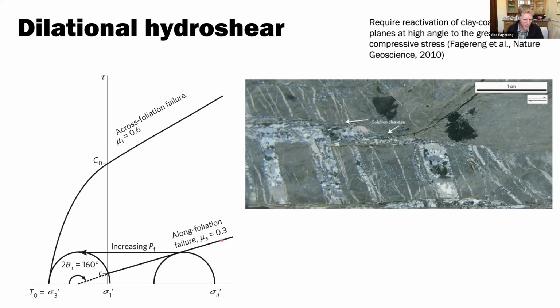But if we think of our cleavage planes, they might have an along-foliation failure criterion that only requires a frictional coefficient of something like 0.3. And that could be activated with a Mohr circle out here. But we generally see evidence for something else. In an example here of one of these shear surfaces, there's generally an optical continuity between the shear surface and tensile fractures, implying that the slip and the tensile opening happen at the same time, in which case we also need to overcome some tensile strength across the foliation, which implies a failure condition more like this, which means normal stress is near zero, shear stress is very low, and we require a very high fluid pressure, at least exceeding the least stress in the system.